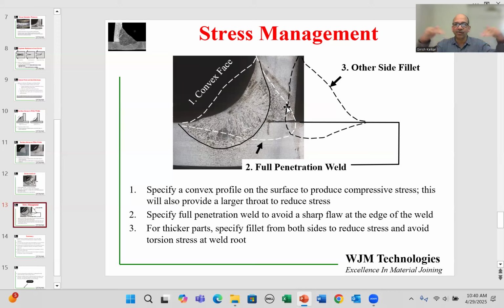So you may have to make a V-groove on both sides, make a weld from this side, make a weld from the other side, and potentially have those two welds overlap. So you have no unwelded section in the middle along the weld interface, or at least have sufficient weld on both sides. So it is distributing the stress over a larger weld area and prevents the weld from reaching that critical stress intensity effect. Okay. So there are multiple things you can do. You can change the chemistry of the weld to reduce the hardness, and you can change the size and shape of the weld to reduce the tensile stress and also to actually avoid this high stress point altogether if possible.